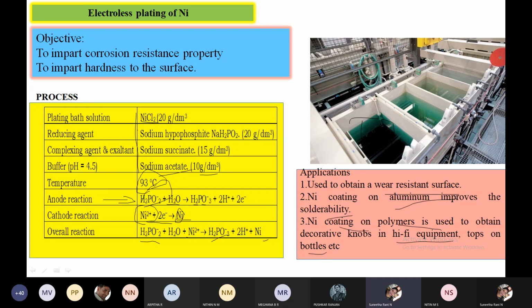The reducing agent we are adding is sodium hypophosphite, NaH2PO2, and the complexing agent and exaltant we are adding is sodium succinate, 15 grams per dm cube. To maintain the pH at 4.5, we add the buffer sodium acetate, 10 grams per dm cube. The temperature we maintain for the coating of nickel is 93 degrees Celsius. After adding all these reagents into the container, the bath solution is prepared.